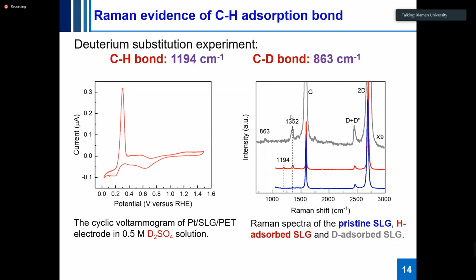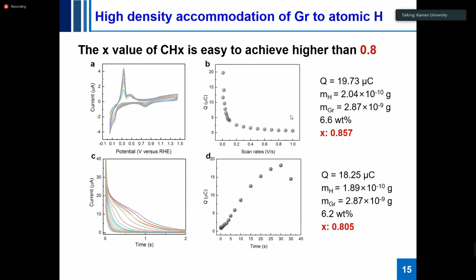And we also did the deuterium substitution experiment. From the Raman spectra in the right figure, we can see that for the pristine graphene, there is no peak below the wavenumber of 500. If we deposit the hydrogen on the graphene, we can observe the sp3 peak at 1352, and also a new peak at 1194. If we replace the hydrogen with deuterium, we find the new peak at 863. So this is evidence of the carbon-hydrogen adsorption bond.